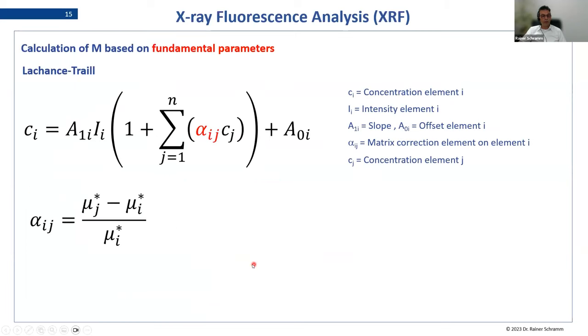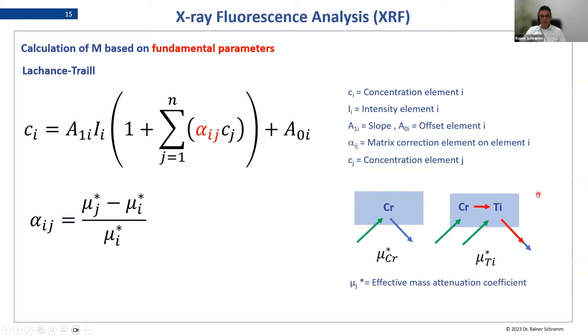And how do we do that? We could use the mass absorption coefficients, which are listed in tables, to calculate this alpha. And what does this mean? So the mass absorption coefficient is a combination of how much chromium is excited in the sample by the exciting beam of the X-ray tube, and how much fluorescence radiation is able to leave the sample to reach the detector. Yeah, so two effects in combination,